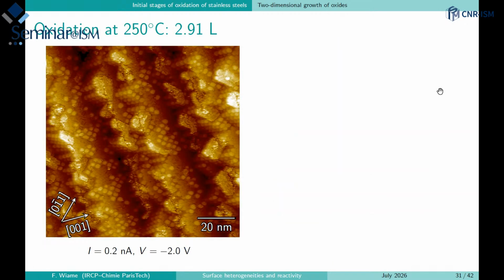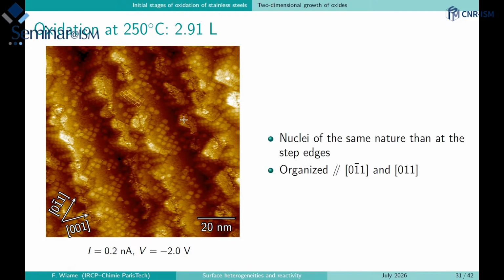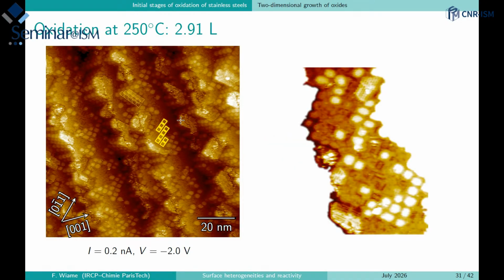So if we are now continuing up to 3 Langmuir, then we can see that the step edges are now saturated, and we start to have some formation of islands which have the same dimension and same orientation as the step edges. So we assume that they are chromium oxide islands, which are formed on the terraces also. And you can see that now we have completely lost the reconstruction. So all the chromium at the surface has been used for creating chromium oxide. And we can also see that these islands are organized. So they are self-organized for the same reason that I showed you on the surface.